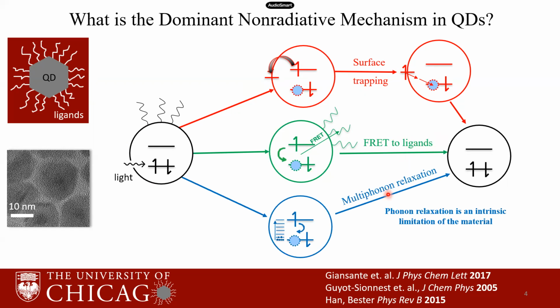The third mechanism is called multiphonon relaxation. The phonons are atomic vibrations of the atoms in the lattice of the nanoparticle. In this model, the electron transfers its energy to form a high order phonon state.